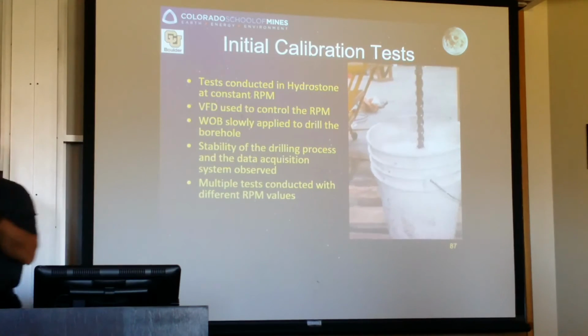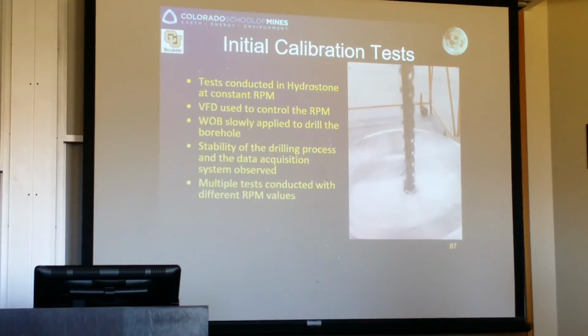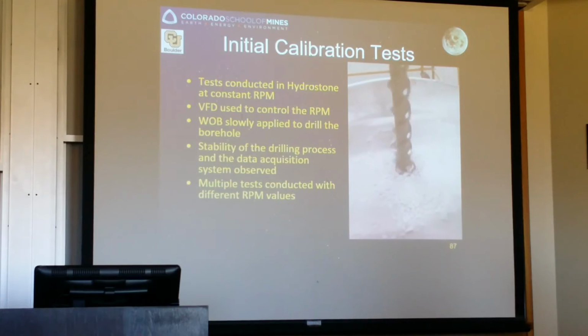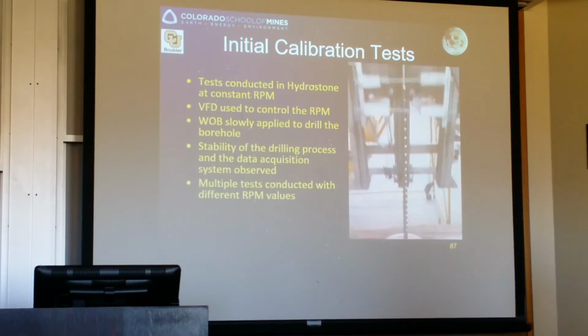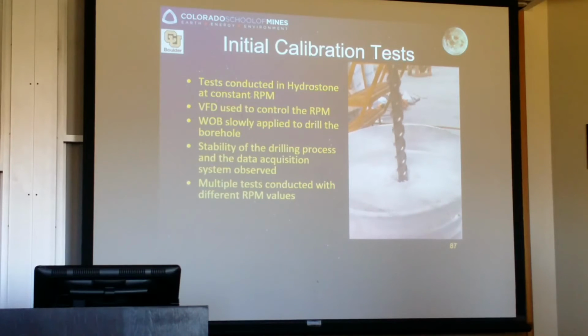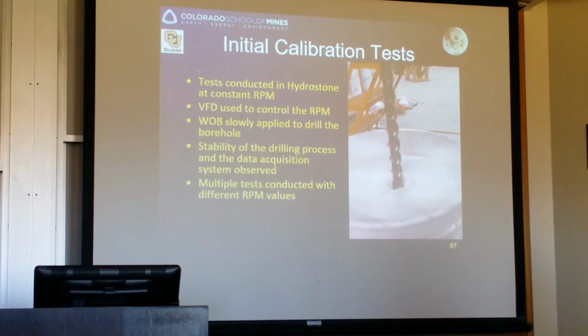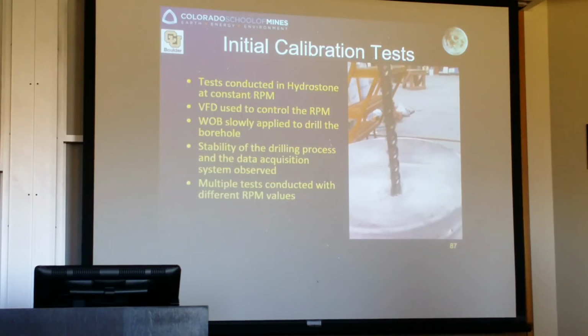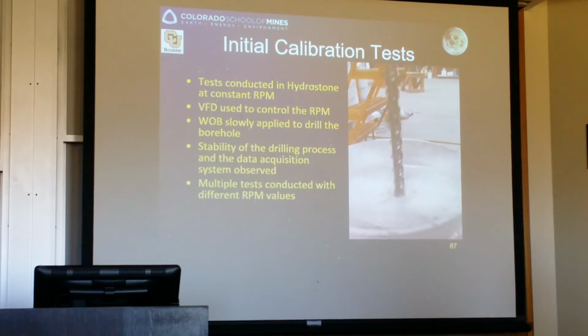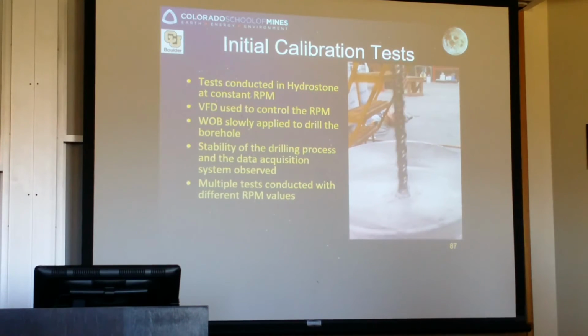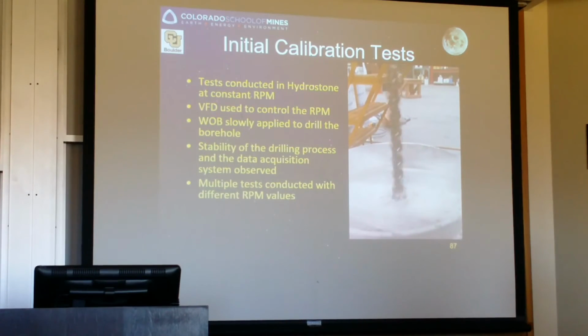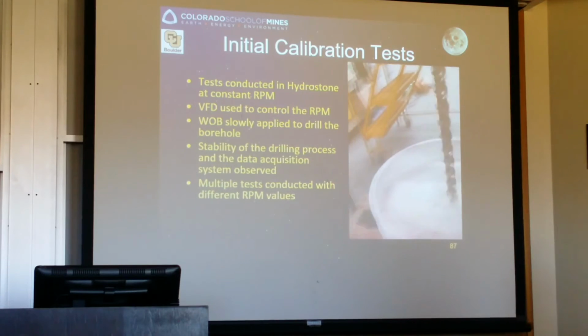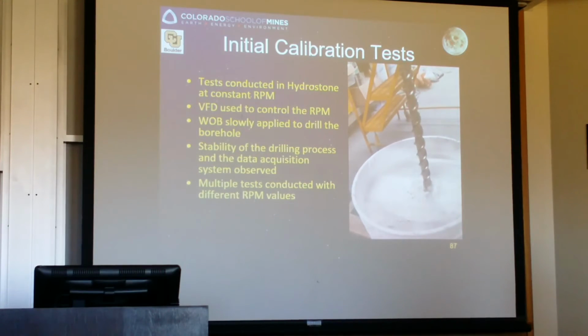and we are going to drill into a simulated frozen regolith, which is made with micro cement. We get base data, and then we'll make a layer cake with the same material but different cement ratios to get different strengths that mimic the different water content. So we'll do a bunch of these blocks and try to get as much data as we can to develop the correlation between machine parameters, drill parameters, and strength. And from strength we get to water, right?